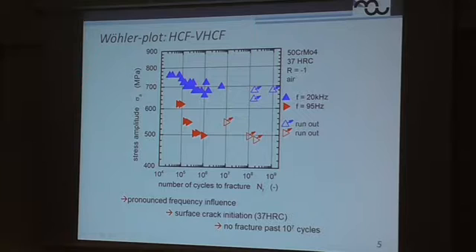So at first I would like to show you the SN diagram that we got from the material under fully reversed loading under laboratory air atmosphere. And it is obvious that we have a strong frequency influence, which can be attributed to a kind of strain rate effect. But additionally, for both cases, whether we have fatigue crack initiation or fracture, we only observe fracture at the surface of the specimens, and we could not observe any fracture above 10 to the power of 7 cycles. But I have to mention that we investigated the specimens after the test, especially the runout specimens, and what we see is a so-called surface roughness, and we relate this to an effective plastic strain amplitude, which leads to somehow fatigue damage.